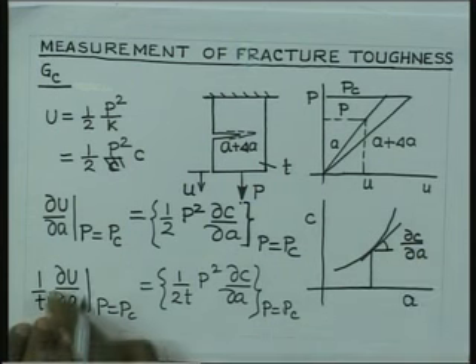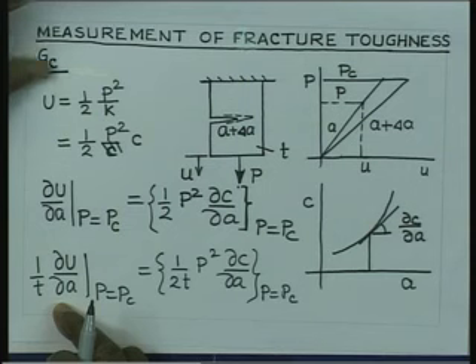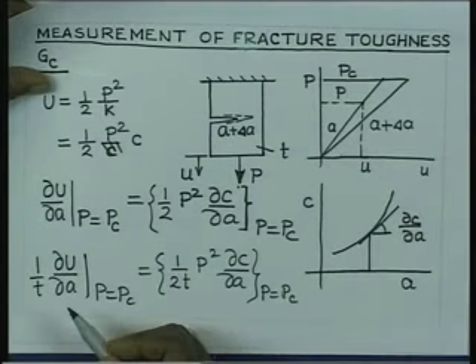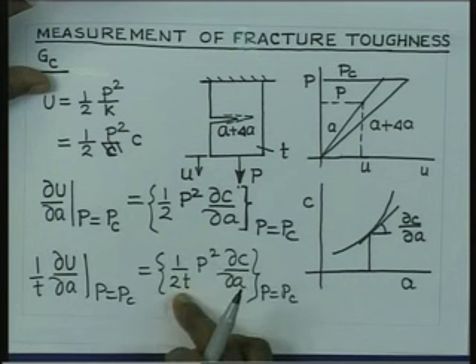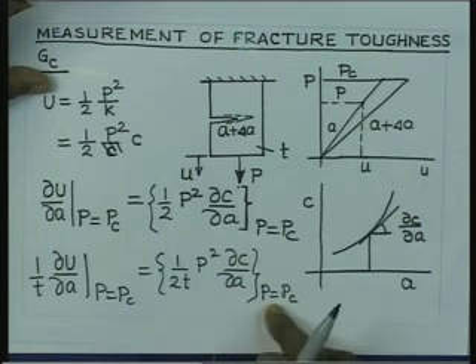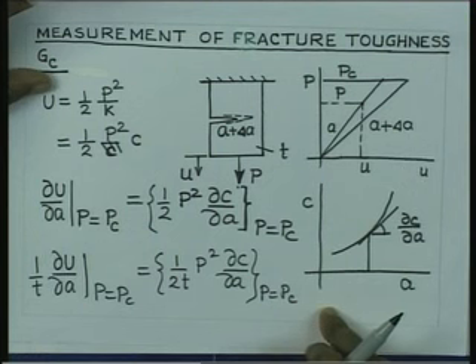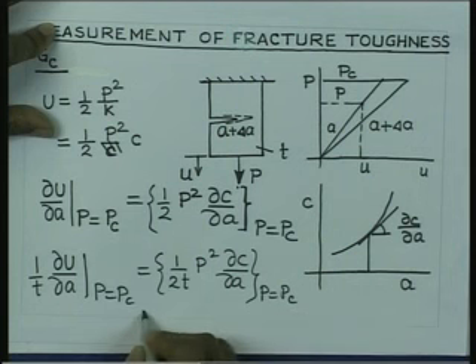and hence the strain energy release rate at the point when the crack is extending is given by 1 by 2 T P square delta C by delta A, where P equal to Pc, that is nothing but the critical strain energy release rate, and this is equal to G C, the fracture toughness of the material. At the point of crack extension, the strain energy release rate is critical, and that is nothing but the fracture resistance of the material. So, in order to determine the value of this fracture resistance of a material, we can do an experiment like this.